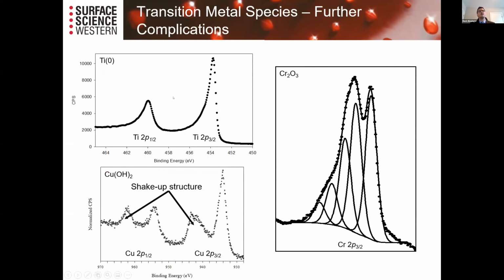So if you look up here, this is a titanium metal. This is the titanium 2p spectra. And you can see that we have an asymmetric peak shape for that metal, whereas something like the oxide would have a simple Gaussian-Lorentzian type peak shape. Copper hydroxide, a copper 2 species, is the classic example for showing shakeup structures. So these peaks here above the main peak are what we call shakeup structure, and they're indicative of a copper 2 species, whereas copper 1 and copper metal do not show these.